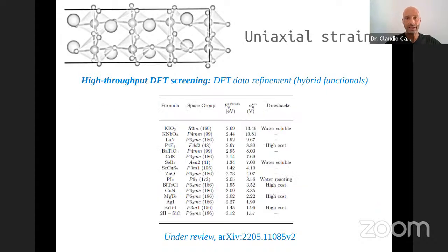By doing that, we come out with our final list of candidates, which are these 16 materials here, among which we can find some that are not really suitable for water splitting, because, for instance, unfortunately, the first material appearing in our list, which is ordered according to the value of the alpha descriptor, the one with the largest descriptor value, is this potassium iodate. However, it has a very good energy band gap and a huge piezo photocatalytic parameter value. However, it's water soluble. So that's for sure not useful for driving any water splitting, because before doing that, it will just be destroyed in the water, in an aqueous environment.